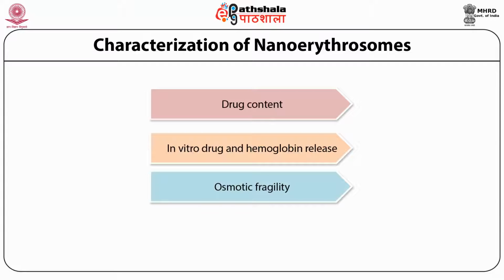Next parameter is osmotic fragility. It is a credible variant for in vitro assessment of carrier RBCs in terms of shelf life, in vivo endurance, and influence of entrapped materials. When erythrocytes are subjected to solutions of different tonicity values, their shape alters in order to maintain osmotic balance. To determine the impact of changing tonicities, the RBCs are subjected to saline solutions with diverse tonicity at 37 degrees Celsius for 10 minutes. The dispersion subsequent to centrifuging at 25 G for 15 minutes is analyzed for drug or hemoglobin release.